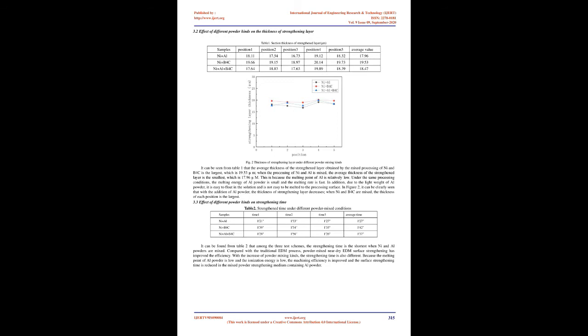When the strengthening powder Ni, Al powder, and B4C powder are mixed as strengthening medium, the high temperature melting and rapid solidification rate between graphite electrode material and matrix material are different, resulting in different morphology of strengthening layer and microstructure growth of strengthening phase.